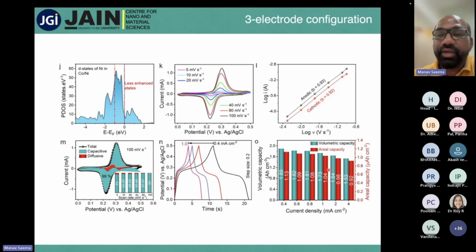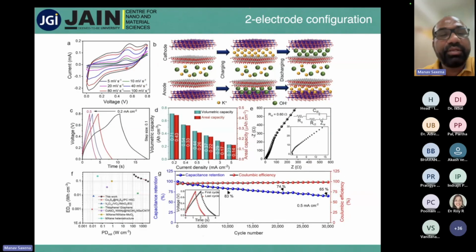And based on the GCD, we have calculated the volumetric capacity as well as the areal capacity of the material. So we have done the two electrode configuration, and we have done the cyclic stability. Cyclic stability even goes up to 30,000 cycles. And we have to keep in mind that the material is only 2 or 3 nanometer thin. So the very ultra thin material is showing cyclic stability up to 30,000 charge and discharge cycles. And the first and last cycle is shown here for confirmation, and it can go up to